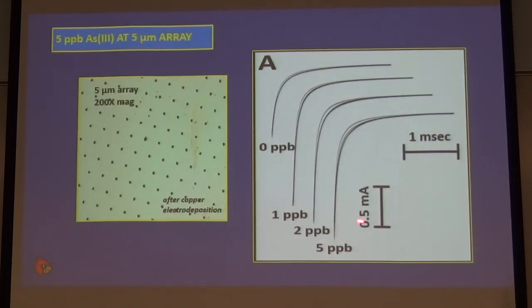We just blow up that 5 micron array system. You can see it more closely. The blank still exists. It's quite a bit smaller than it was before. But you can see that we can now confidently look at much lower concentrations. Now we're in the range we really need to be.